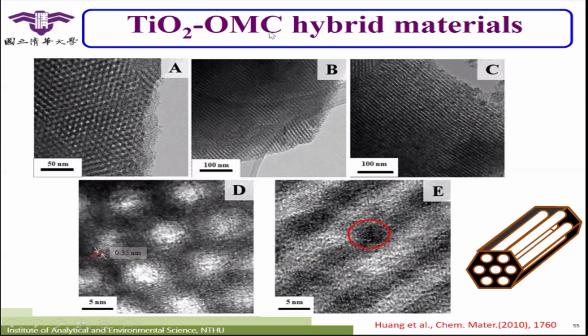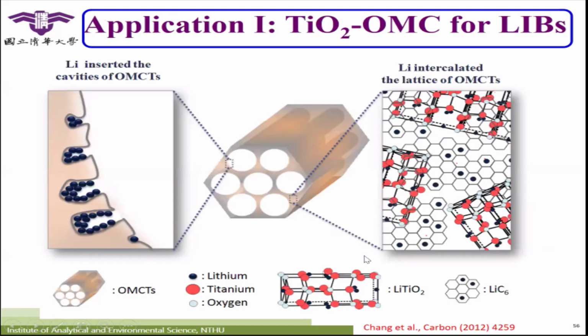You can put any kind of metal oxide inside, TiO2, ZnO, and some others. We use this for lithium batteries. We have the highly ordered structure, and it has pores, so that the lithium can be stored in the pores. When you do the discharge, the lithium ions go inside and outside. They can go inside the TiO2 and also inside the carbon.